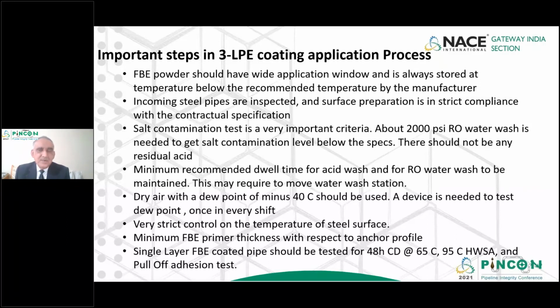So that is why there's a pressure requirement that at least 2000 psi of RO water is needed. So again, because people can choose different times for how much to wash, the specification provides a guideline on the minimum dwell time when we still need to be in contact with acid, and the time needed to wash with water.